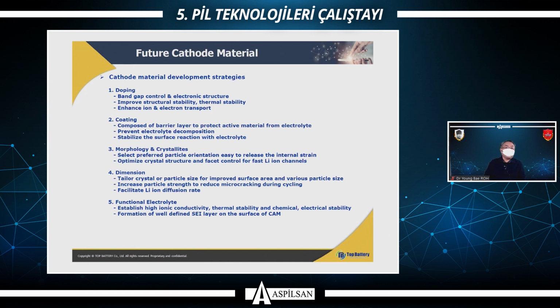Through morphology and crystal structure control, we have to select the preferred particle orientations, easy to release the internal crystalline strain, and to optimize the crystal structure and the facet control for fast lithium-ion channels. Tailoring crystal and particle size is a crucial factor to facilitate the lithium-ion diffusion rate. Also, a functional electrolyte is important to build the SEI layer on the surface of cathode material. It leads to enhanced electrochemical stability of cathode material, especially high nickel cathode material.